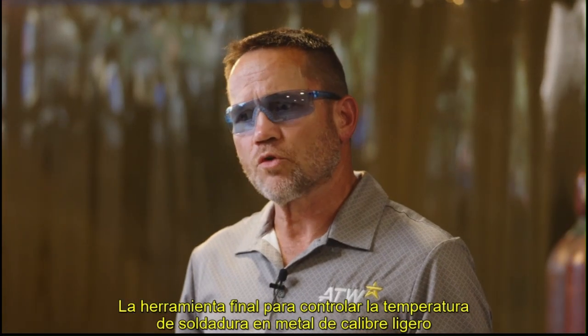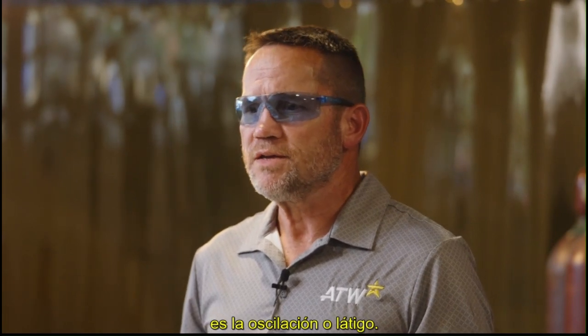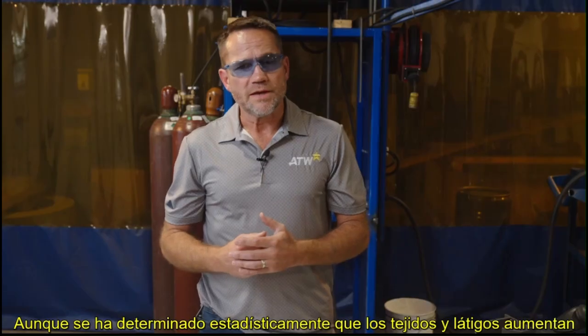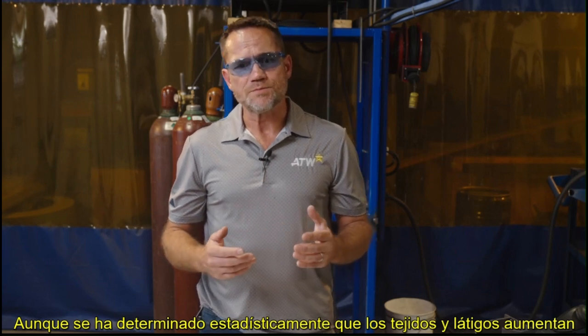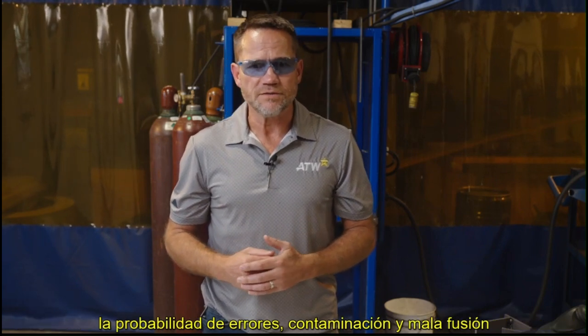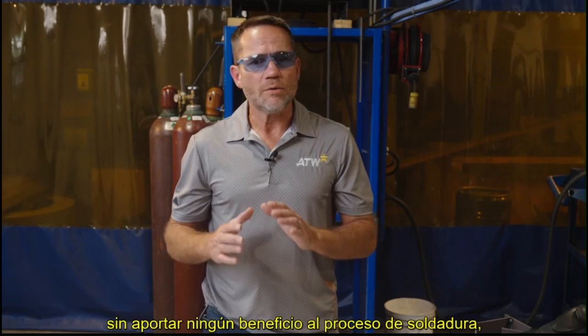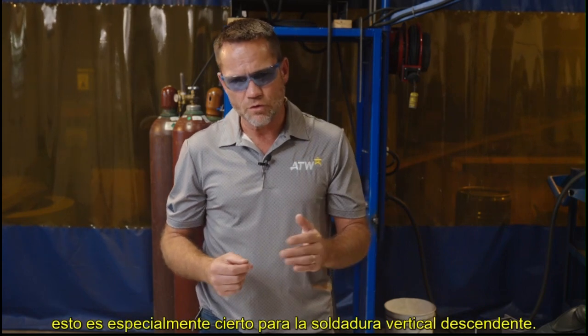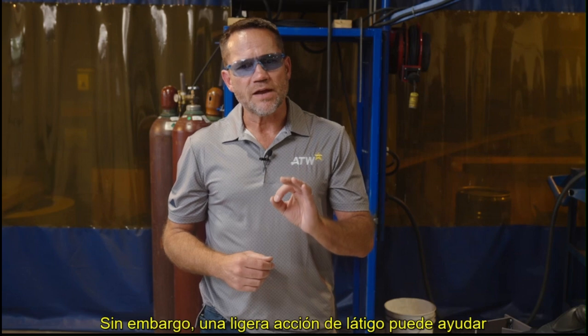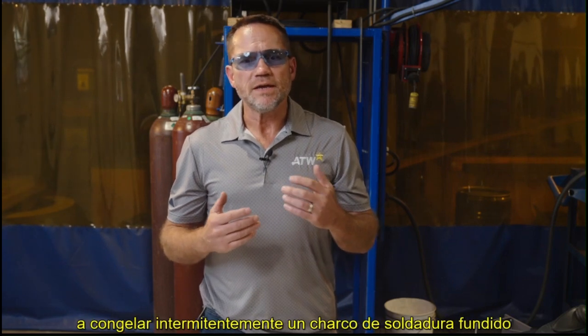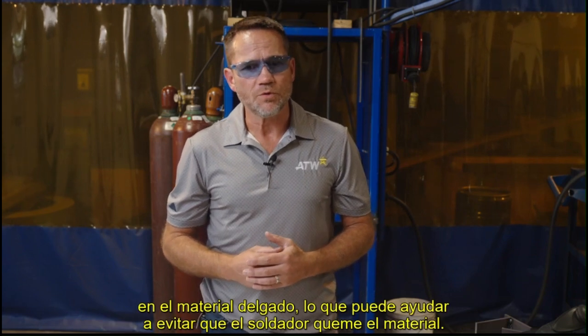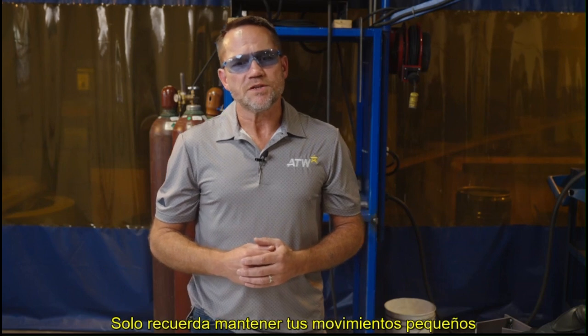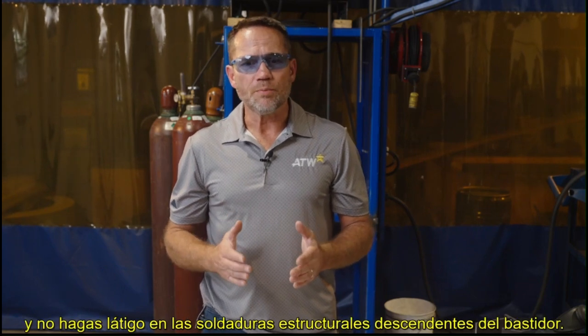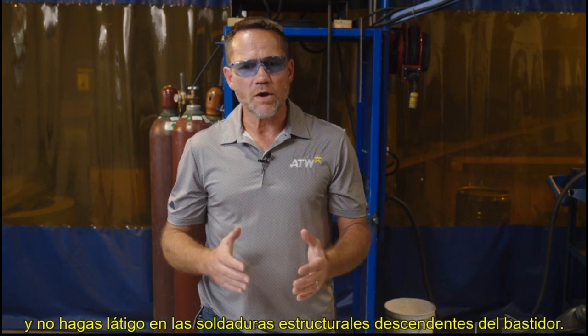The final tool to control welding temperature on light gauge metal is oscillation or whipping. While it has been statistically determined that weaves and whips increase the probability of errors, contamination, and bad fusion without bringing any benefit to the welding process, this is especially true for downhill vertical welding. However, a slight whipping action can help to intermittently freeze a molten weld puddle on the thin material, which can help keep the welder from burning through. Just remember to keep your movement small and don't whip on downhill structural frame welds.